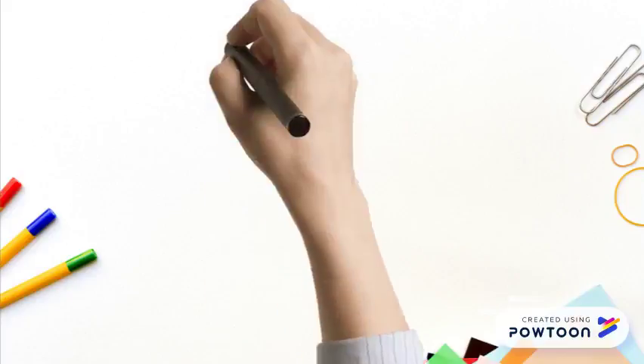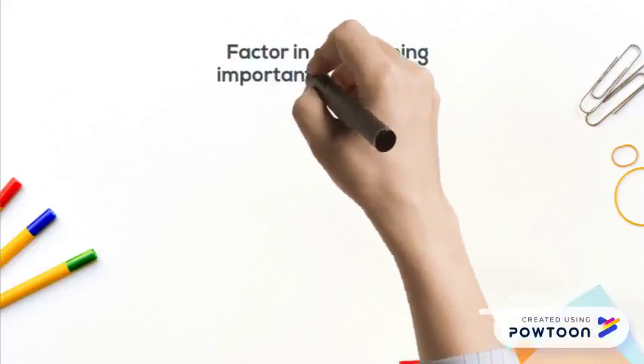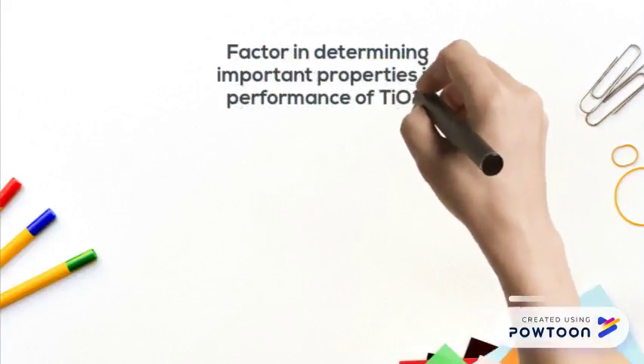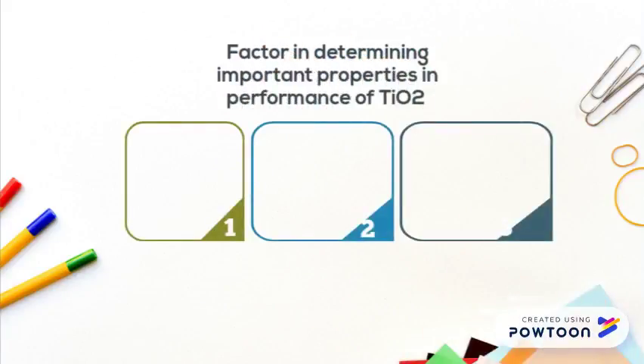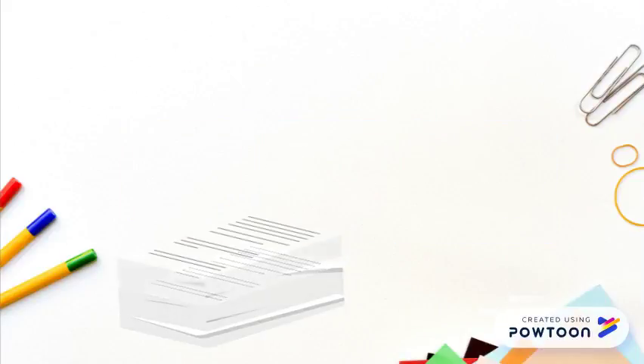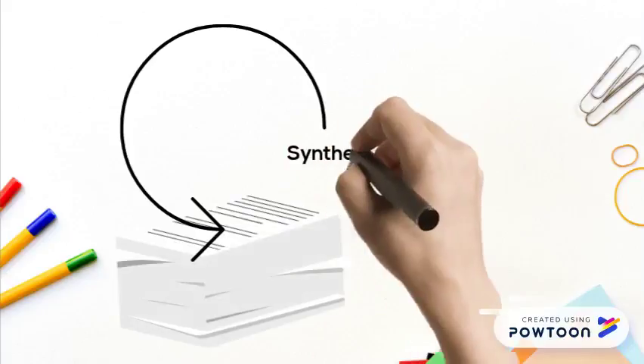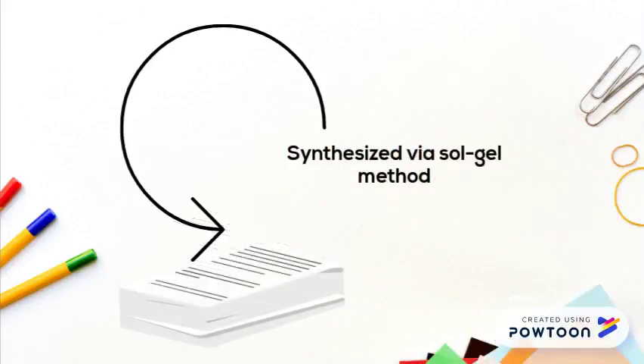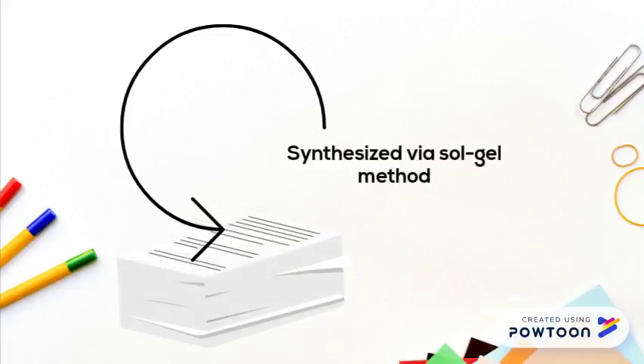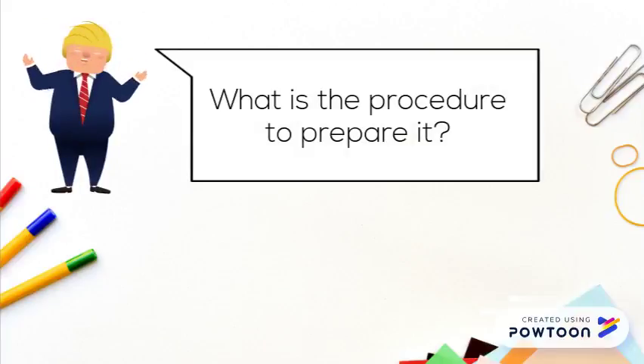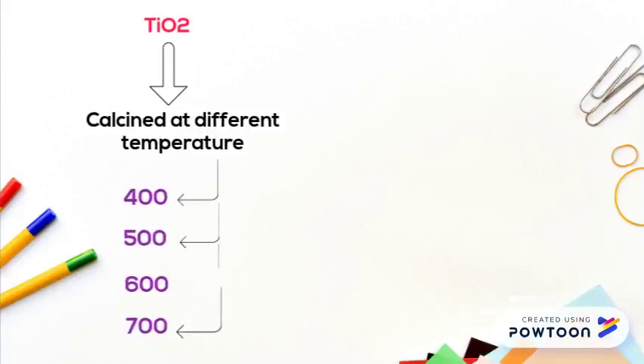Therefore, there are several factors in determining important properties in the performance of titanium dioxide for application, such as particle size, crystallinity, and morphology. In this journal, titanium dioxide nanoparticle catalyst was synthesized via the sol-gel method using titanium tetraisopropoxide as a starting material, calcined at different temperatures, which are 400, 500, 600 and 700 degrees Celsius.